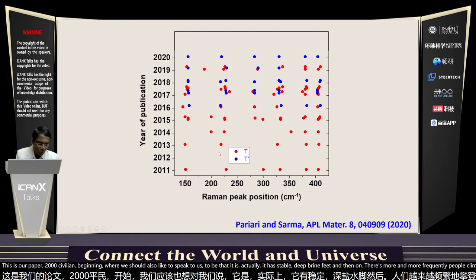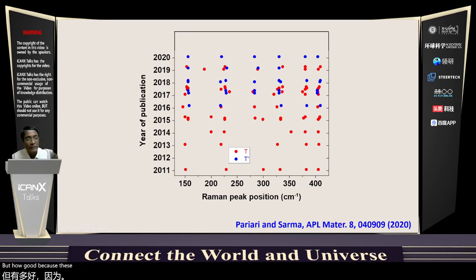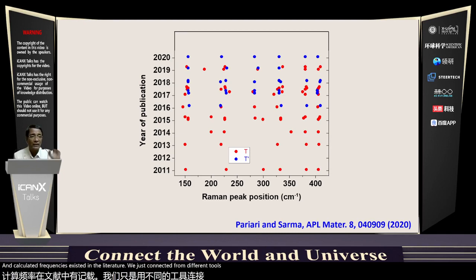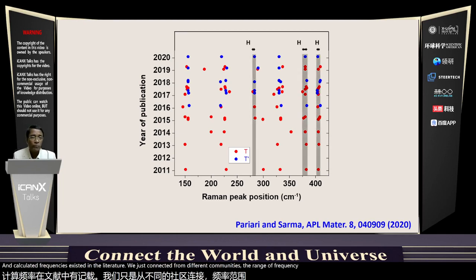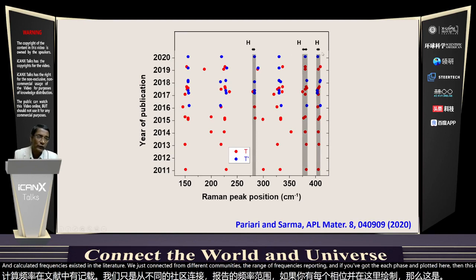But how do I know? Because these frequencies can be calculated. And calculated frequencies existed in the literature. We just collected from different theories the range of frequencies reported. And if you collect the H phase and plot it here, then this is a range of reported H phase.